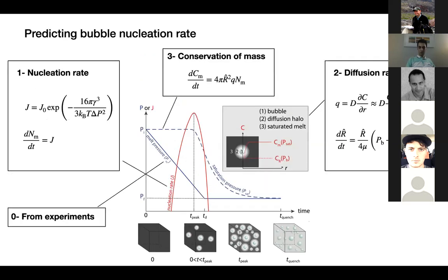Now, to simulate these processes within samples, first we get pressure conditions from experiments as a known condition. We estimate nucleation rate using classical nucleation theory as a function of supersaturation pressure. Bubble number density is estimated by integrating nucleation rate through time. We use a diffusion model to estimate diffusion flux. We take a mean field approximation. We use the Rayleigh-Plesset equation to estimate bubble growth rate.